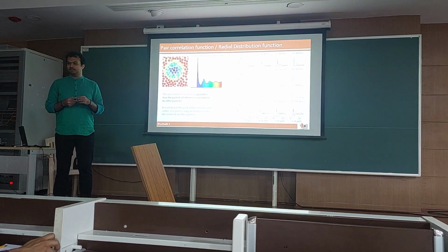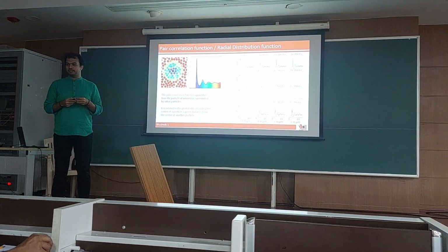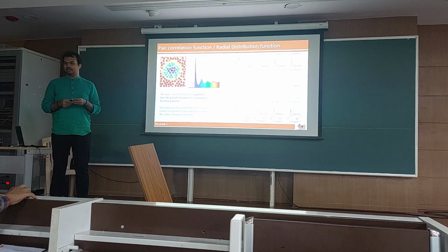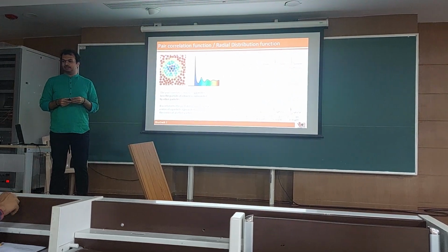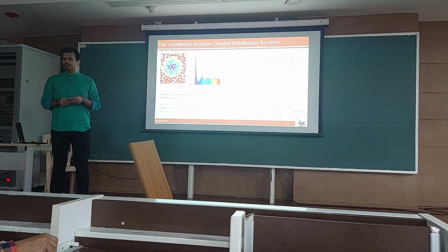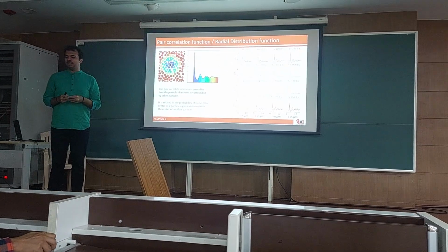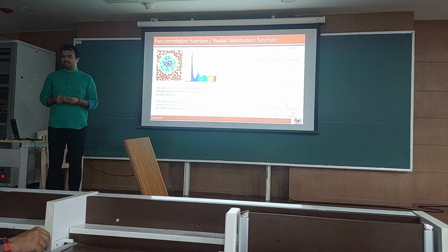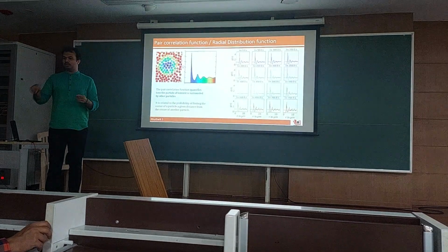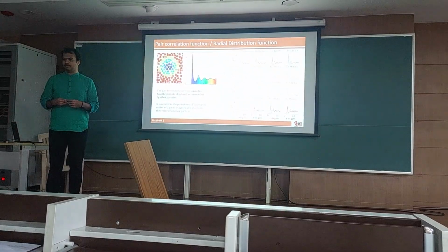So you think that the plastic deformation will annihilate some of the defects that were present, so suppose I do it 3-4 times, finally I may realize that there are no defects now. Yeah, it's possible. You can call it mechanical annealing, like thermal annealing, where it goes to the minimum more and more.